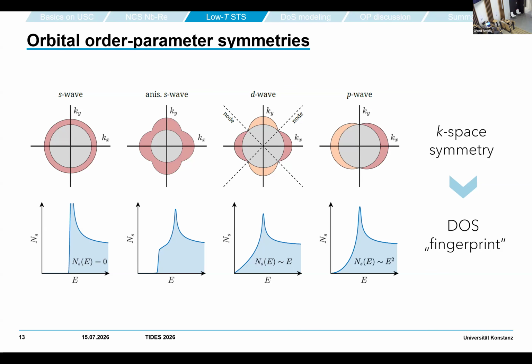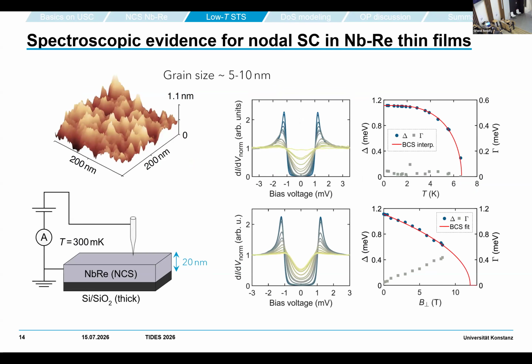So this is our approach. We started with thin films of niobium rhenium, thickness typically 20 nanometers, roughness about 1 nanometer. For most spots we see a fully gapped spectrum, compatible with BCS. There's a temperature dependence shown here, deducing the gap with the Dynes model. We need a very small Dynes parameter, but it can be reasonably well described by BCS. Also when we study them in perpendicular magnetic field, it can be described as a BCS fit, with the pair breaking accounted for by a Dynes parameter.